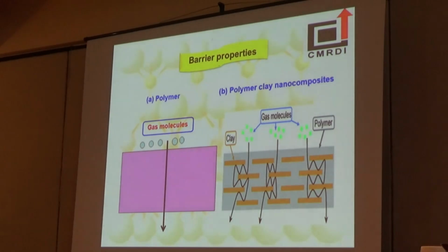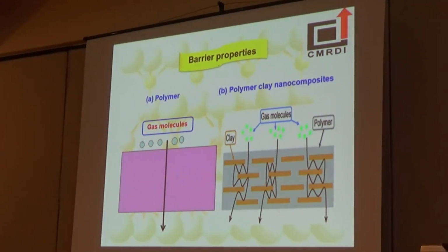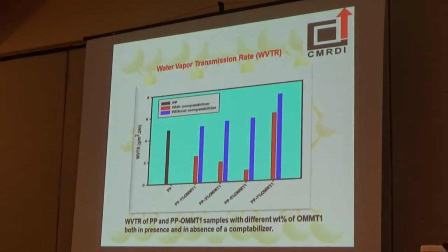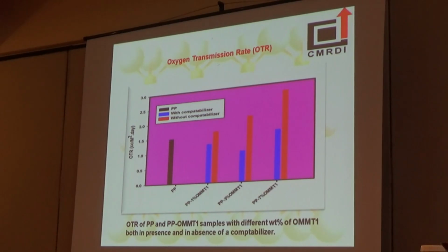Barrier properties. For a material to be used in packaging application, it must have barrier properties. But for a polymer, its barrier properties are very bad because it has high permeability for gas molecules and water vapor molecules. In case of polymer clay nanocomposite, the path of the gas molecules and water molecules will be more difficult through the composite structure. By measuring the water vapor transmission rate, we can see that by increasing the amount of organically modified clay, the water vapor transmission rate decreases. The same is observed for the second series.